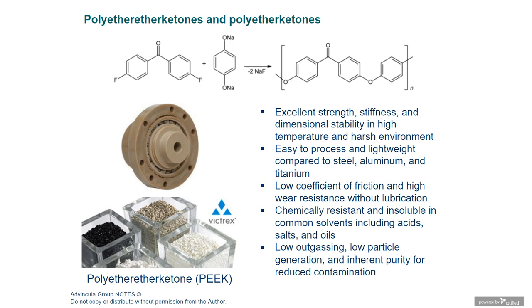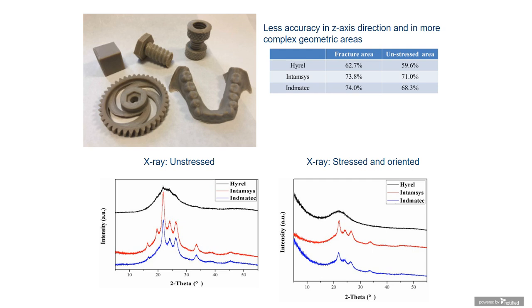Polyether ether ketone is a very important high performance polymer that we have 3D printed, and we have recently reported its properties based on various printing methods and compositions. Here you can see that we have printed these polyether ether ketone samples with 3 different printers utilizing a commercially available polyether ether ketone filament. And they have various types of crystallinity as shown here.